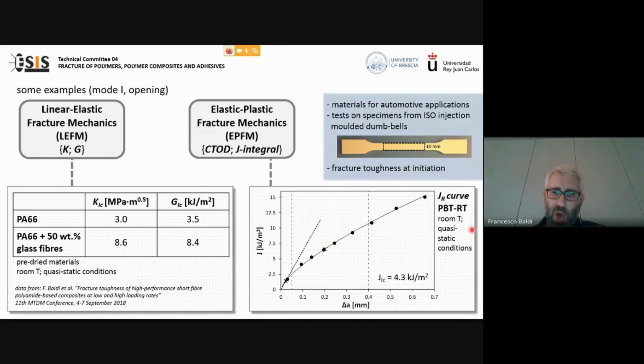Of course, on this PBT, I couldn't apply the linear elastic fracture mechanics, not because of the fact that it is viscoelastic, but simply because of the fact that the degree of ductility exhibited by this material was too high for the application of the linear elastic fracture mechanics. I mean that the linear elastic fracture mechanics approach could not be considered valid.